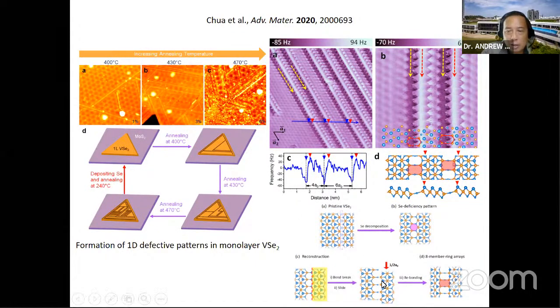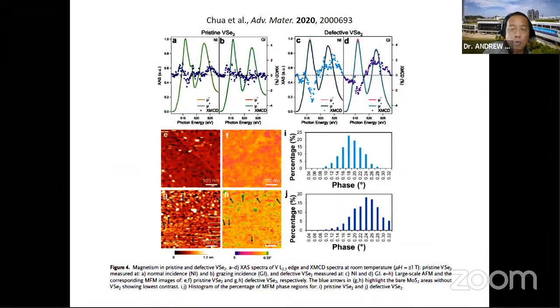And we have worked out the detailed atomic structure of these line defects, which have a missing row of selenium. And then with both the intrinsic and the selenium-deficient sample, she did MFM measurements, which are shown here, as well as XMCD measurements, which are shown above. You can see that in the XMCD, pristine vanadium diselenide, as we had shown before, is not magnetic. But in defective vanadium diselenide, you can see a larger dichroic signal here. Similarly for MFM, on top is intrinsic and the bottom is defective, and you can see an increase in these green color regions, indicating that defects of some sort seem to be inducing localized magnetism in the images.